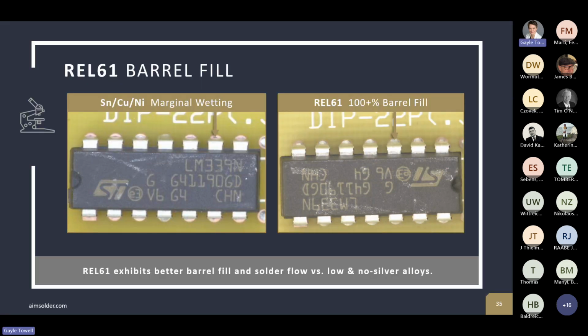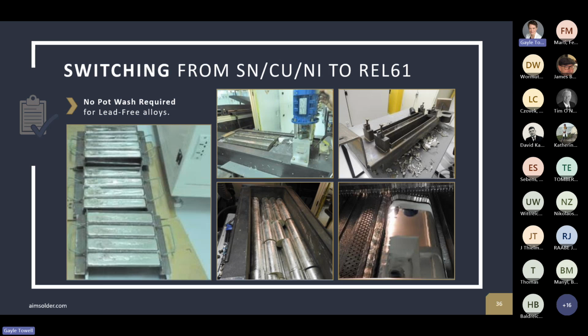REL61 again has very good barrel fill. It tends to flow very well, right? It has that improved wetting. Tends to outperform a lot of the low no silver alloys that are on the market. Sometimes people ask about switching their pot to REL61. If you're already using a lead-free alloy, there's no pot wash required, so it can be fairly straightforward.